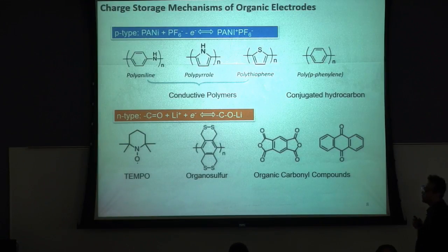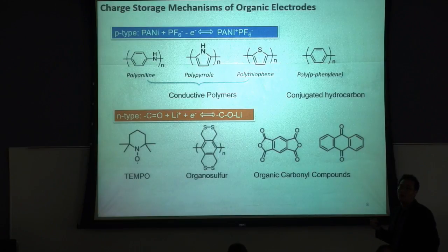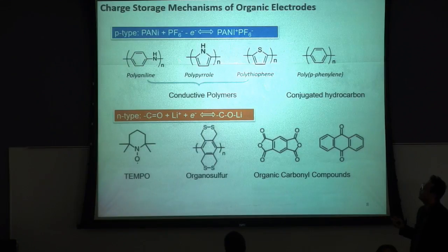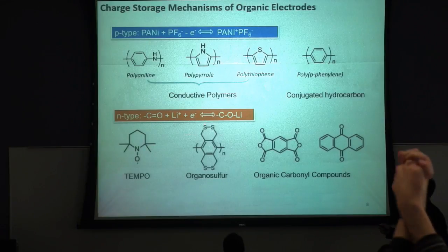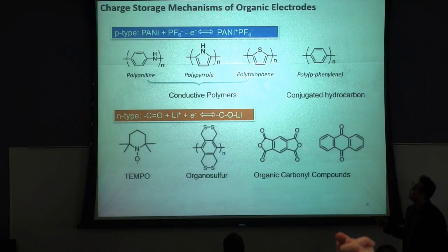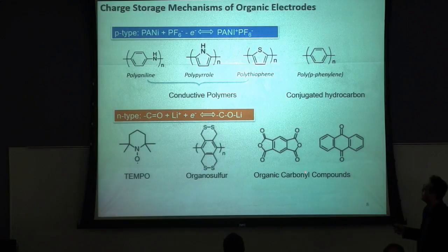Then, if I consider the charge storage mechanism of this kind of organic electrode material, first, there are p-type charge storage mechanisms. This is for conventional conducting polymers. In a conventional conducting polymer, if we remove 1 electron, we can store 1 anion on the backbone of this polymer. We call this the p-type or anion doping or anion insertion charge storage mechanism. On the other hand, the n-type charge storage mechanism directly reacts with lithium ions, so it can store 1 electron. One of the most representative examples is organic carbonyl compounds. This kind of carbonyl molecule can react with lithium, and we can store 1 electron.